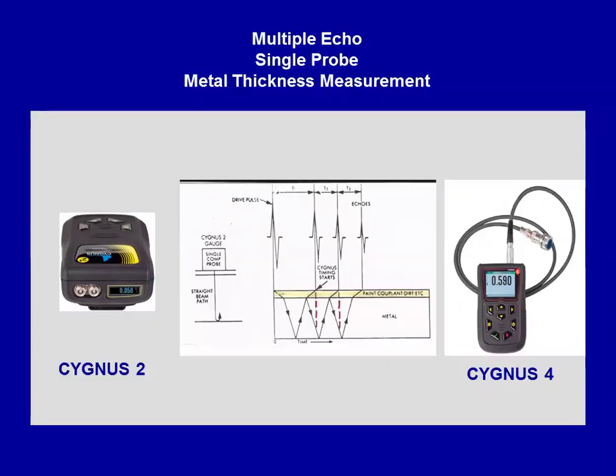Now, when you can't match the timings between the second and third echoes, and there could be a whole bunch of reasons, the gauge says, wait a minute, the timings didn't match. Let's say you had severe pitting on the other side, and the sound is ricocheting and bouncing around. What happens with our gauge is it goes blank. We'd rather upset you and give you no information than lie to you and give you false information. So the good news is our gauges always give you a measurement when they should, and won't give you one when they shouldn't. That has its own set of headaches as well, because nothing is 100%.